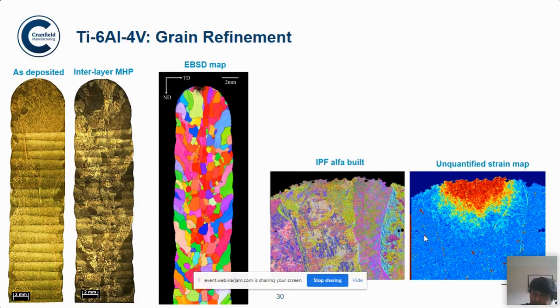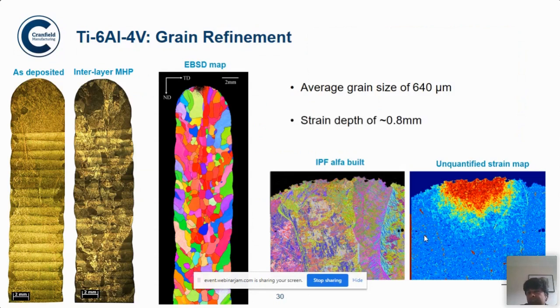And this is the strain map and the inverse pole figure of the build that is shown. So the average grain size reduced, and the strain depth was measured, up to what depth the machine hammer peening is inducing the strain, because as I said, it is done in cold condition, and you have to have a proportion of the layer height and the straining that you can induce.